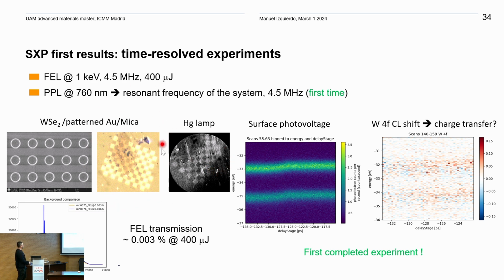This is the picture that we measured in the momentum microscope with a mercury lamp, and you see here that there is some different contrast, and this is because the tungsten diselenide is not just single flakes. Sometimes you have many flakes. And then to establish time zero, the first experiment that you can do is to measure surface photovoltage, and this has a time scale in the picosecond, and from there, by fine tuning, you can determine what your real time zero is for femtosecond experiments.